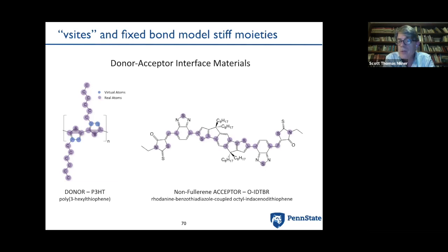And it's made of rigid moieties too, and so only the purple atoms are necessary to specify the orientation of the non-flexible bits. And then you've got a few dihedral angles between them, and those are the important degrees of freedom. So we represent this thing with very few, relatively speaking, real atoms, with the other ones determined by the position of those real atoms. And the stiffer the thing is, the better it is for us: the fewer atoms you really have to let have their own equations of motion.